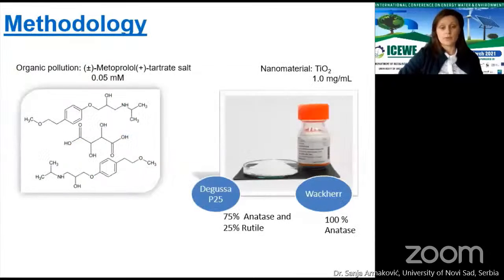Metoprolol is a selective beta blocker that is used to treat a variety of cardiovascular diseases. Metoprolol shows slow direct phototransformation and hydrolysis. Because of this fact, metoprolol is a good example for our study. It was detected in all kinds of environmental water, and also in drinking water in some countries. For the purpose of photocatalytic degradation of hazardous pollutants in water, titanium dioxide has been recognized as the most preferable material due to the high photosensitivity, non-toxic nature, and stability.